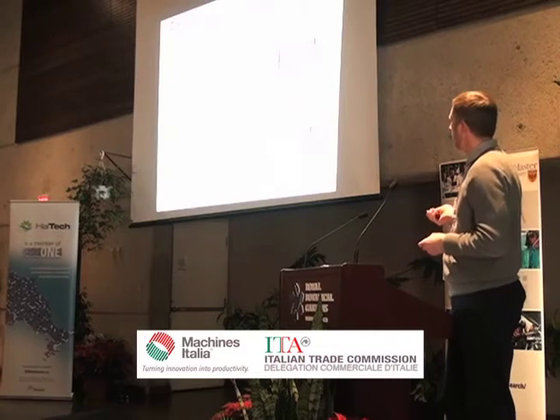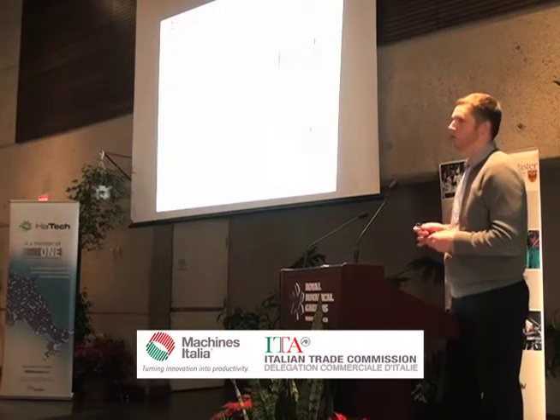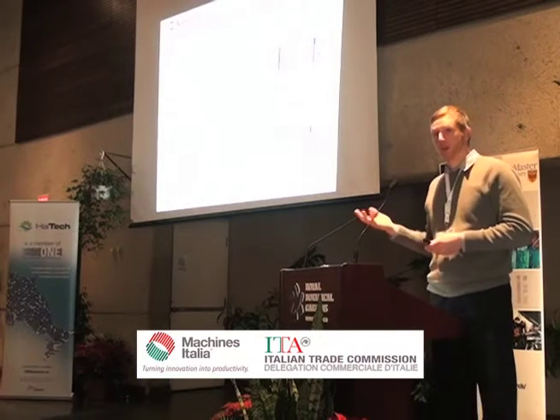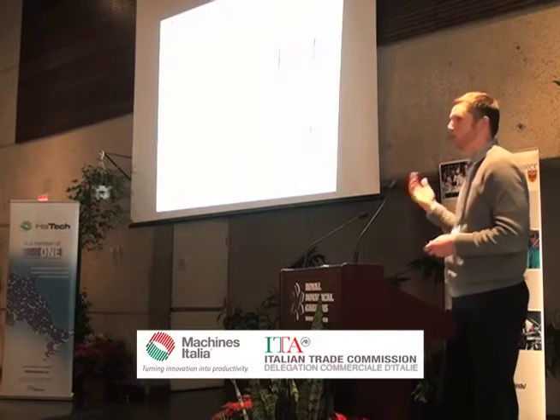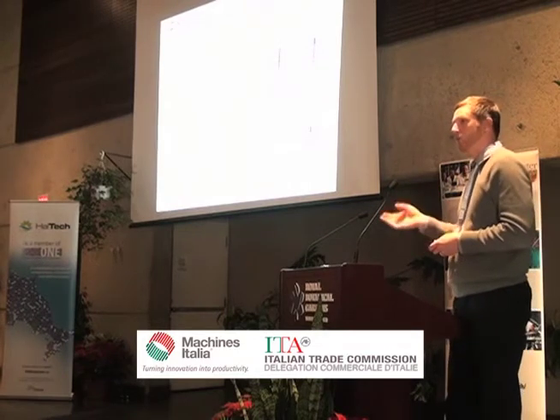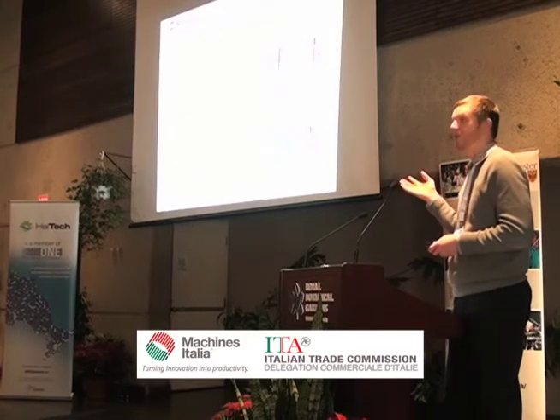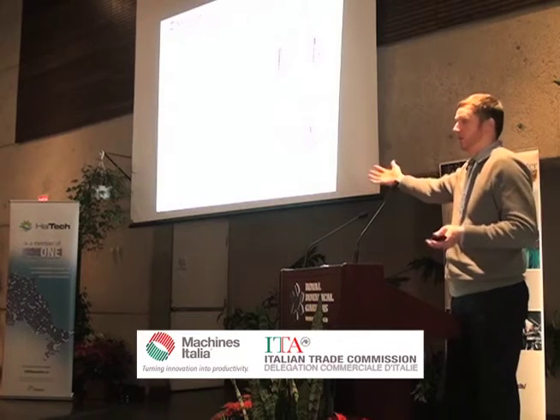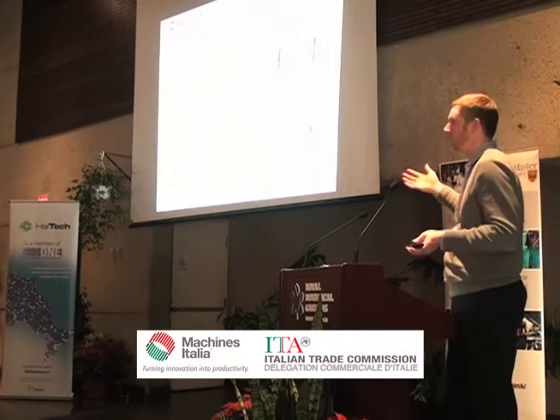But what we're able to do is, the base patents around the technology were that you use a pulse plating approach, and that way you're always introducing the nucleation phase as opposed to the grain growth phase. And if you maintain that, as well as through our proprietary bath chemistries, you're able to keep the grain size of the material very, very small, down to the 20 nanometer range. You're able to do that for essentially infinite thickness and keep the properties uniform.